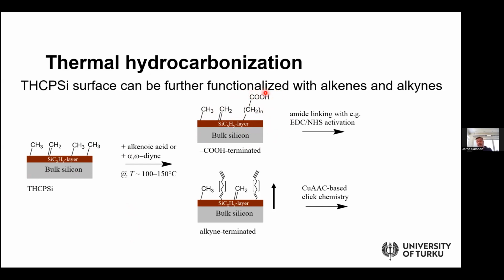And this carboxylic acid group is very good considering future functionalization, because you can easily activate that and link the amine into it. And we have some other click chemistry systems and things like that. There are quite a lot of different routes to functionalize this thermally hydrocarbonized surface further.